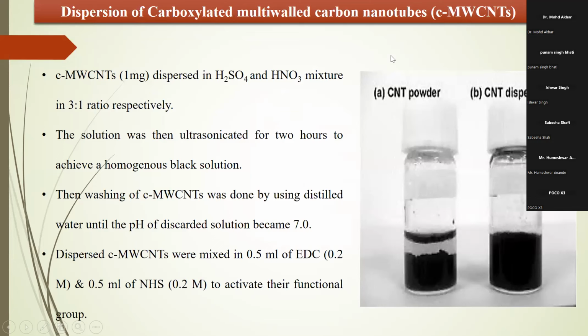I also took the multi-walled carbon nanotubes as a composite, and following their dispersion and washing, the dispersed multi-walled carbon nanotubes were mixed in EDC and NHS solution to activate their functional group.